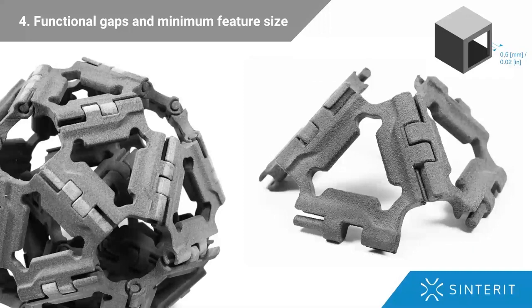Another factor that you should consider, at least in case of some prints, is the feature size. Usually, you shouldn't go thinner than 0.8 to 1 millimeter. There are exceptions focused mainly around the purpose of the printed geometry. Details on figurines, architectural or medical models can be as thin as 0.5 millimeters, while loaded elements will probably have to be thicker than that, not to break, for example.